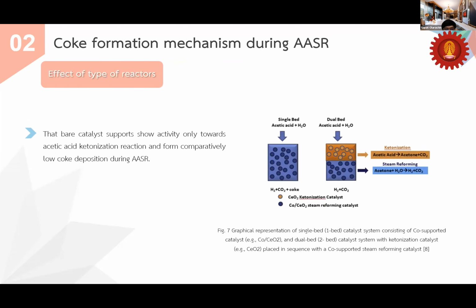Okay, and then the effect of the type of reactor. A modified dual bed system in series for AASR. In figure 7, the bare catalyst surface shows activity only toward the acetic acid ketonization reaction and forms comparatively low coke deposition during AASR. In the case of the dual bed configuration utilized for AASR, in the first bed acetic acid is converted to acetone via the ketonization reaction, which further undergoes steam reforming in the second bed. The improved stability of the catalyst system could be because the steam reforming of acetone results in less coke deposition in contrast to acetic acid, and also there was an increase in the steam to carbon feed ratio.